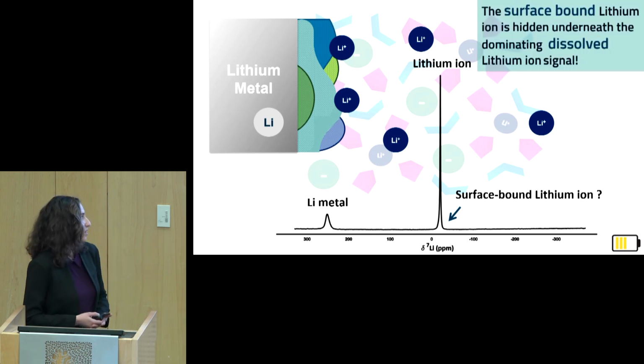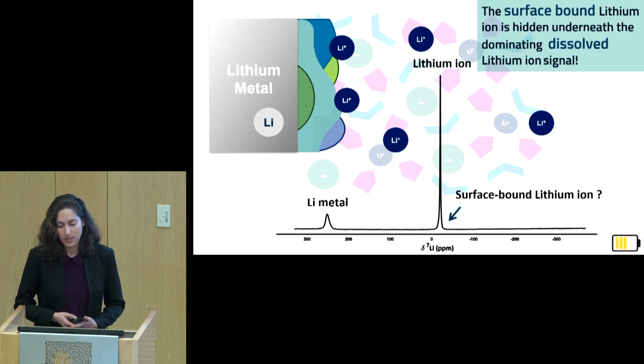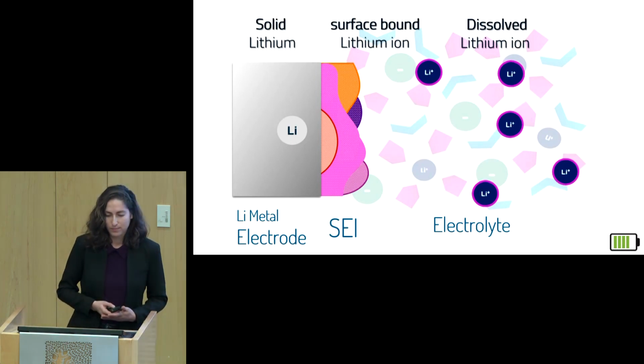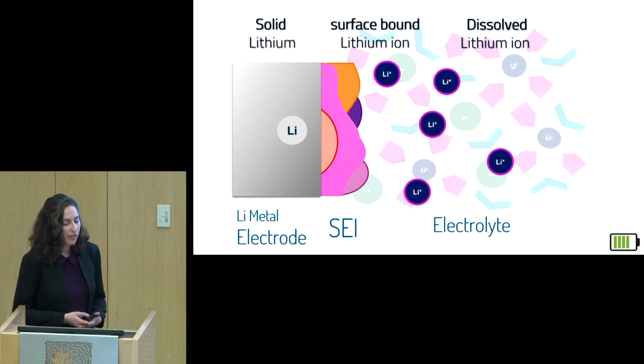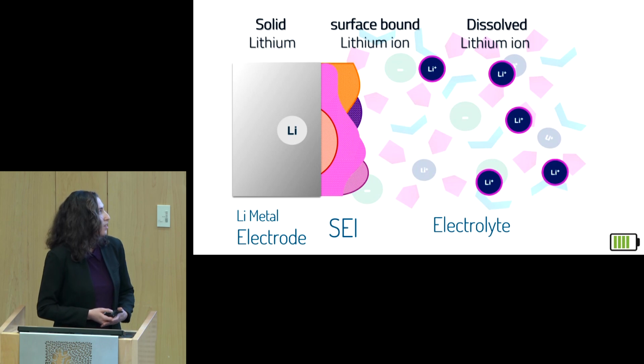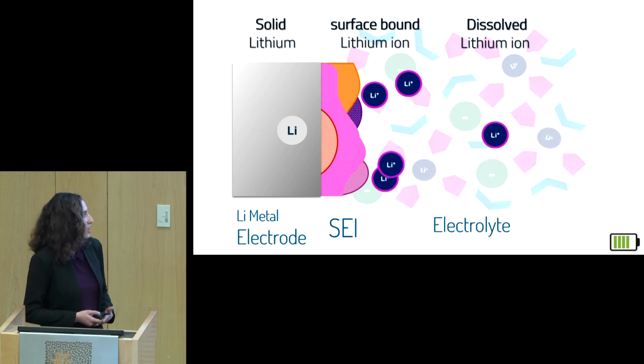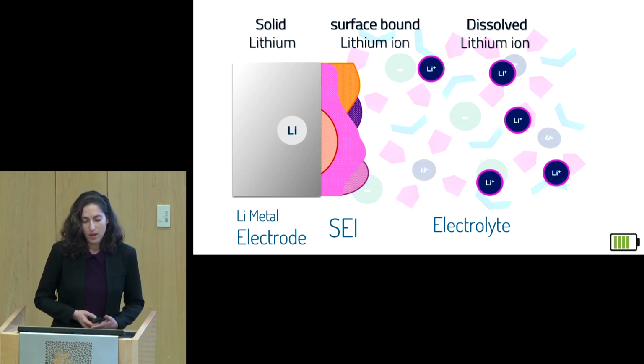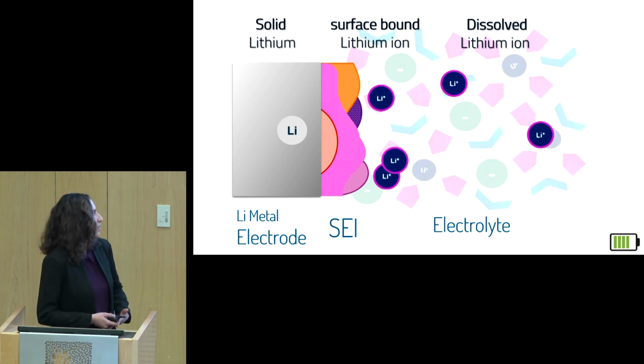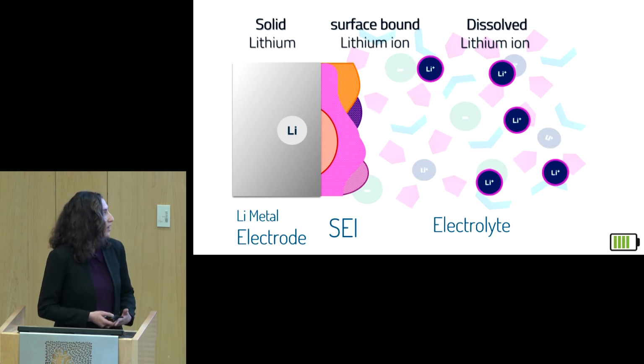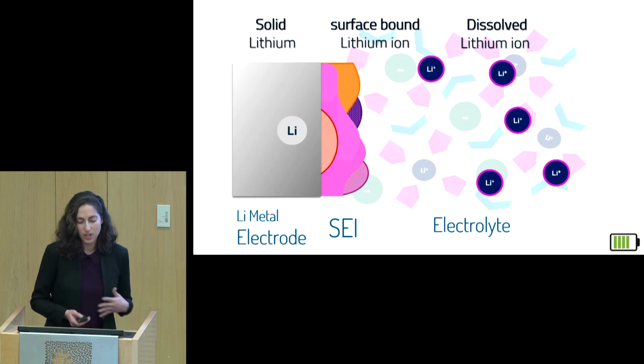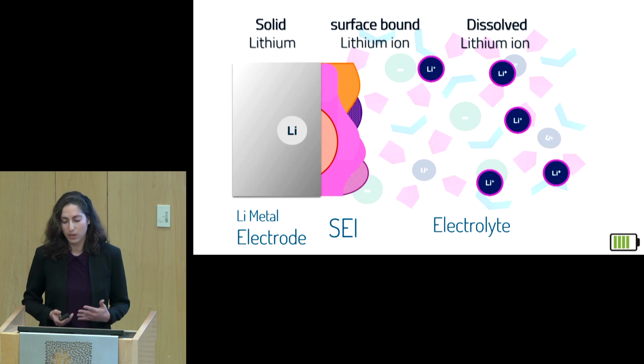The signal of the surface-bound lithium is hidden underneath the dominating signal of the dissolved lithium ion. So it can't be seen with a simple measurement. But we know that these environments are always in exchange. The lithium ions are always attaching and detaching from the surface. So maybe I can't directly measure the lithium ions that are bound to the surface, but I can utilize the exchange between the two environments. Because the lithium ions are always exchanging between the two environments, it must have an effect on the NMR signal.